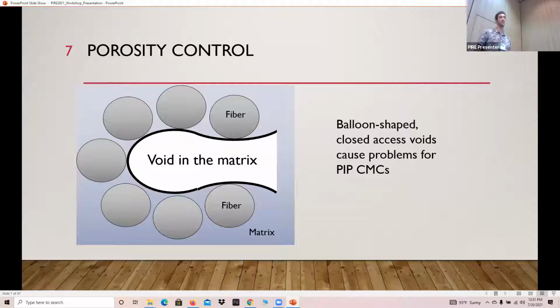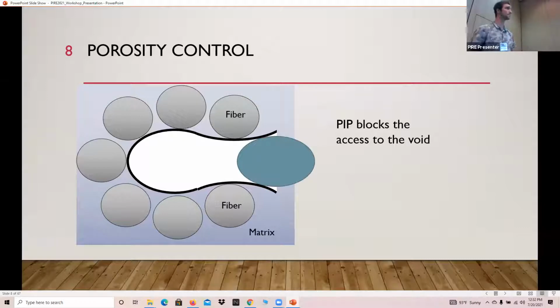Of course, with a CVD process, they're very energy intensive and very long, but you don't have this issue. However, we're looking to a pre-ceramic polymer PIP process that allows for a fully dense matrix buildup as well as this porosity. So again, that's just what we can see here.